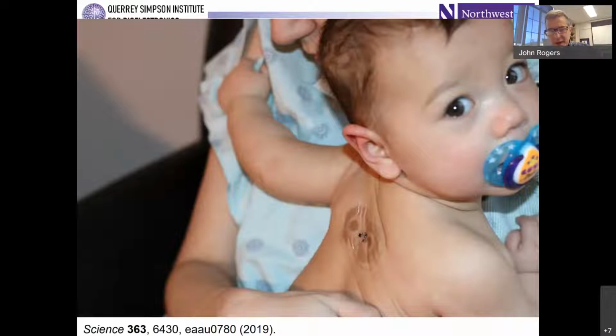This is a device that's been mounted on the baby's back. Turns out you can measure cardiac activity from either the chest or the back. And you can see as the baby rotates around to look at the cameraman in this case, the skin of the back wrinkles in a natural way, and the device wrinkles right along with the skin. So there's very little mechanical load, very little mechanical constraint associated with natural movements of the skin imposed by the device itself. And the other consequence of that is that you don't need a very strong adhesive interface to keep these devices mounted on the skin.